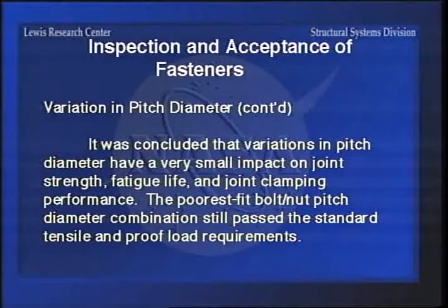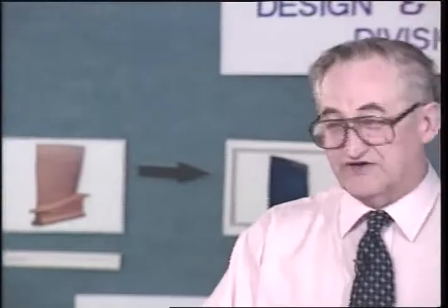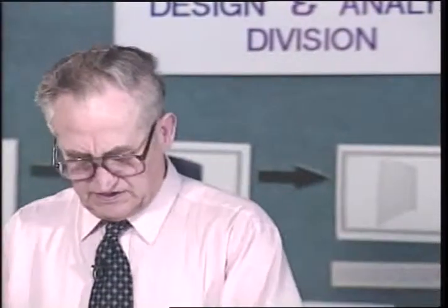The conclusion was that variations in pitch diameter don't have a very big effect on joint strength, fatigue life, and clamping performance. In other words, it can be out of tolerance quite a bit and still pass the standard tensile and proof load requirements, which surprised a lot of people. Because varying the pitch diameter, you are loading your threads unevenly. But evidently what happens is that, though you are loading them unevenly, you are spreading the load around to where you get more yielding and it will still carry the load.